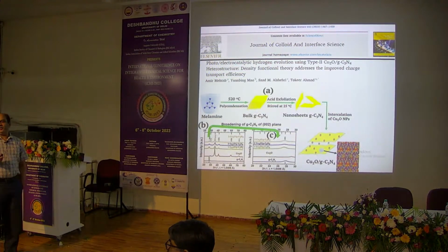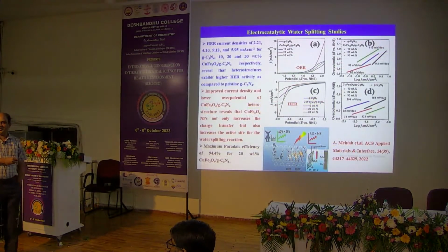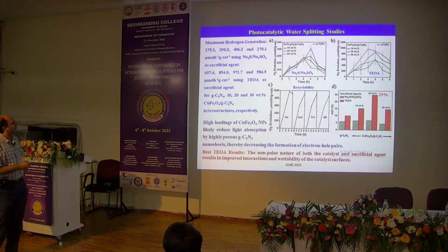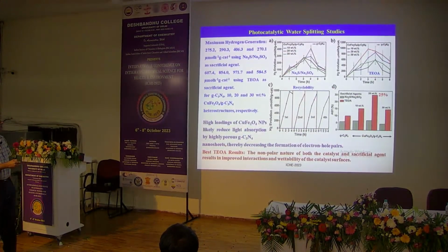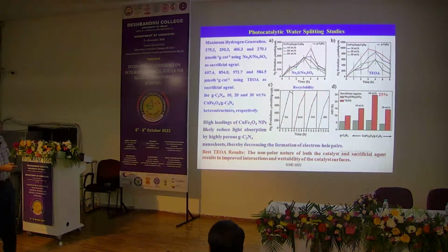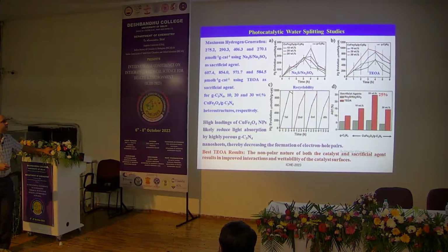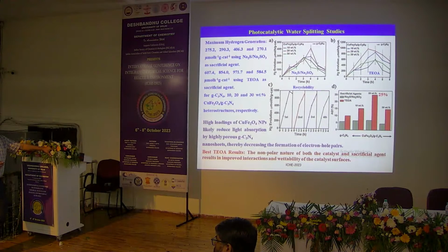Actually, we obtained this comment from the reviewer also. I will show. Plot C, the recyclability data. In the first cycle, up to 3 hours it's increasing and again it's decreasing at the 4th hour. Is it because of some saturation effect or what? Yes, some saturation effect as well as the loss of the sacrificial agent as time passes. With the help of PL and other investigations, we have responded to this query. Okay, excellent. Thank you.